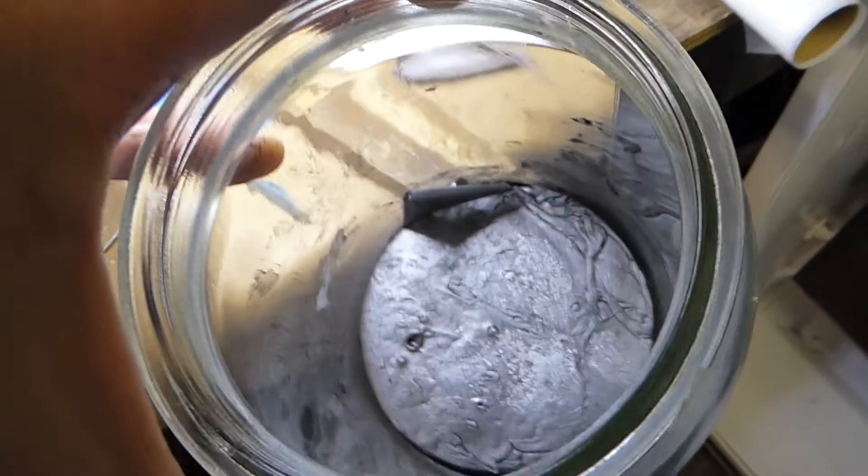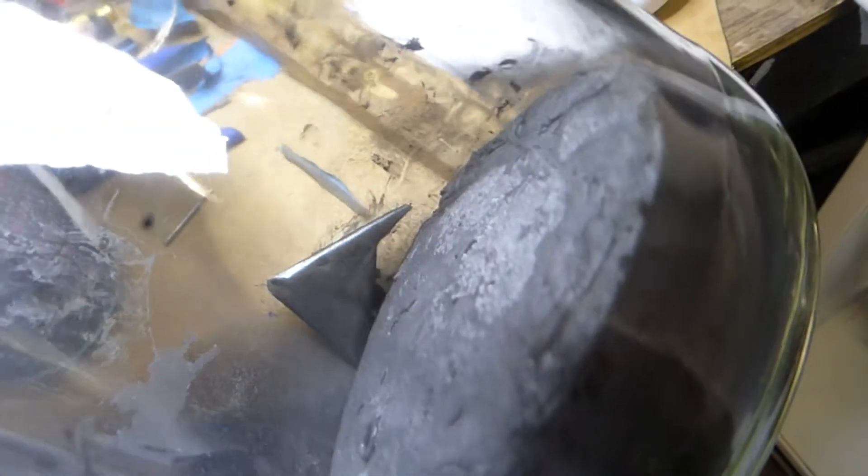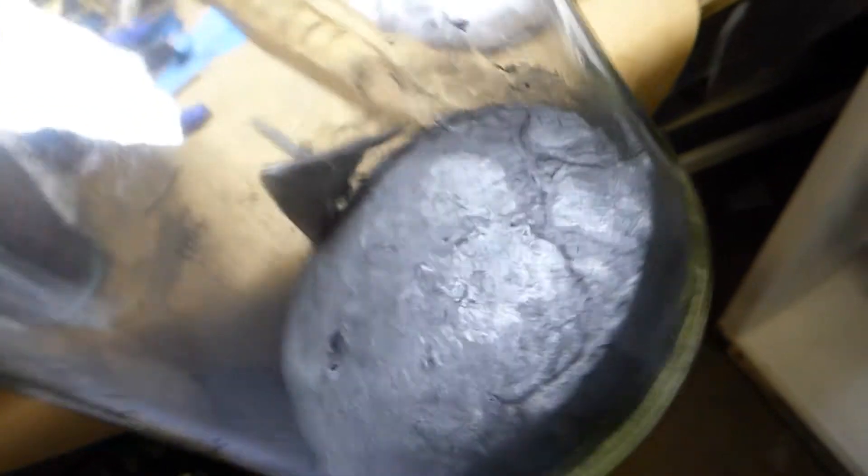Here's an interesting little failed experiment. This is polystyrene foam that was melted down in acetone. I put some graphite in there - actually it was mass fraction graphite graphene sonicated stuff. I mixed it up and laid it out and tested the conductivity of a piece of it, and there was nothing from end to end.